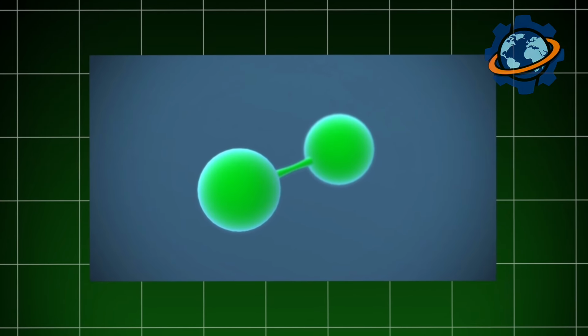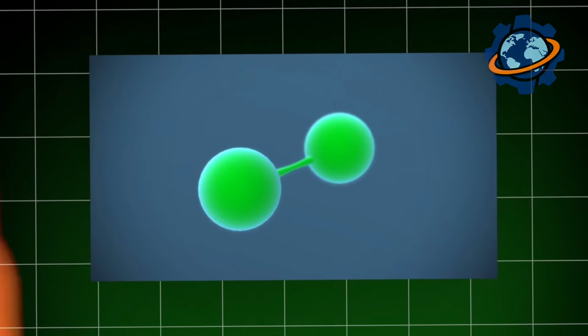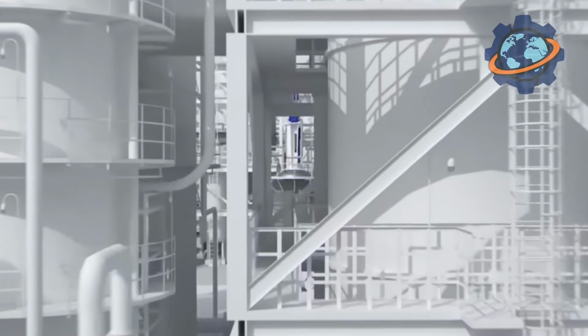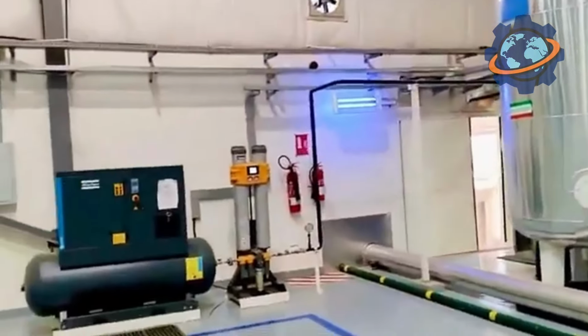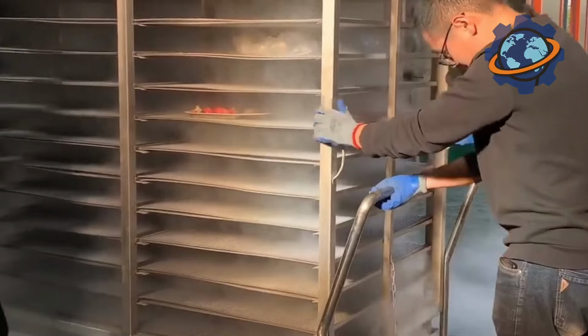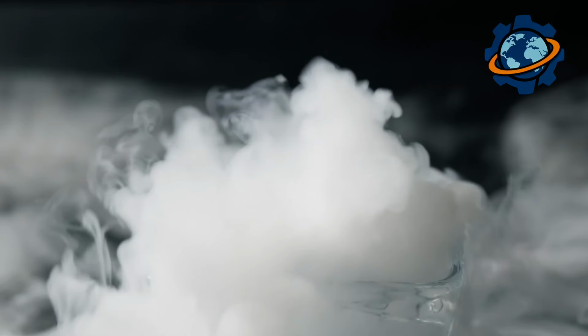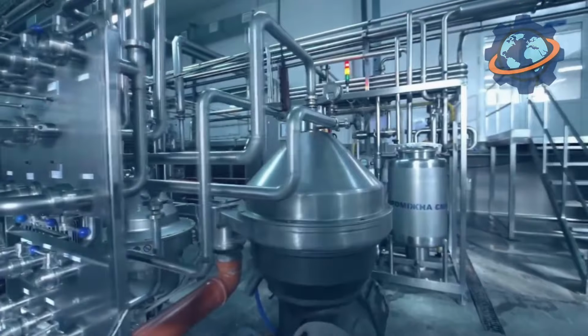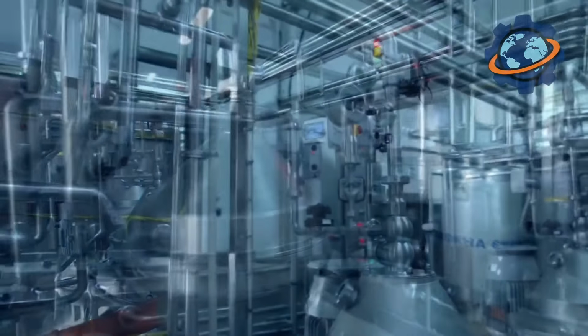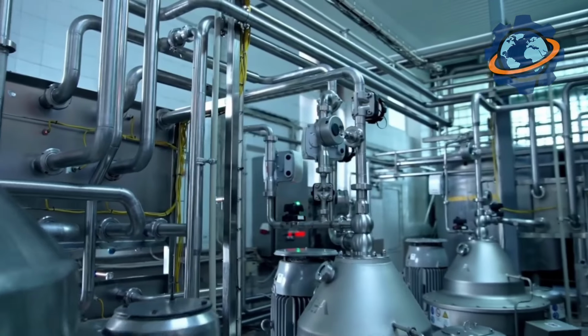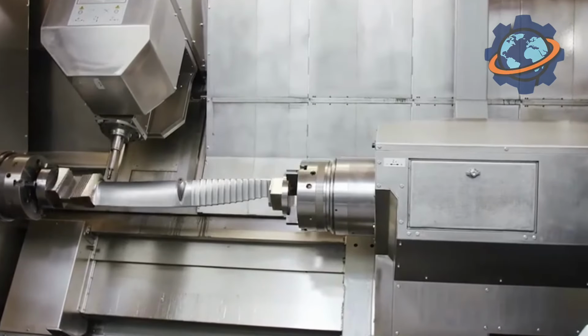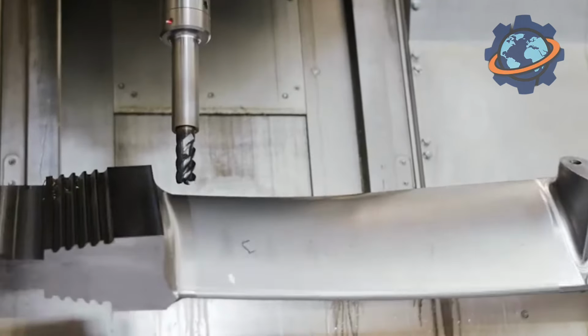Then comes the thermal barrier coating, yttria-stabilized zirconia ceramic applied atom layer by atom layer using electron beam physical vapor deposition. In vacuum chambers, electron beams vaporize ceramic ingots. The vapor condenses on rotating blades, building up a coating 0.08 of an inch thick with a columnar microstructure full of microscopic pores. These pores act like thermal insulation, trapping air pockets that reduce heat transfer. The ceramic coating lowers blade temperature by 400 degrees, the difference between survival and meltdown. Modern engines couldn't exist without this coating technology.